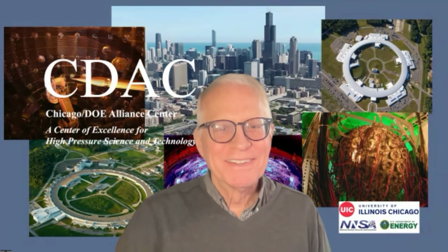I see. Okay. But either way, that's another thing we're tracking. So we just track the orientation of the diamonds with every measurement we make. I see. And if you show up with your own diamonds, you should know the orientation of the diamond relative to the cut then. We get it for free from the diffraction. But you measure it there, on the fly.